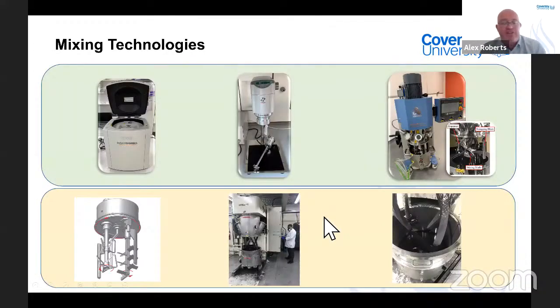So, mixing technologies that I would typically use and that can be encountered. On the top, we've got the mixing technologies that I use in my laboratory at the moment. And these are fairly common throughout the supercap and battery industry. On the left-hand side, you have the Thinky Mixer by Intertronics, which is an off-centered planetary mixer. So it works in a very similar method to a planetary ball mill, but without the balls inside there. So you have an off-axis rotation of a cup, which induces very, very high shear forces.